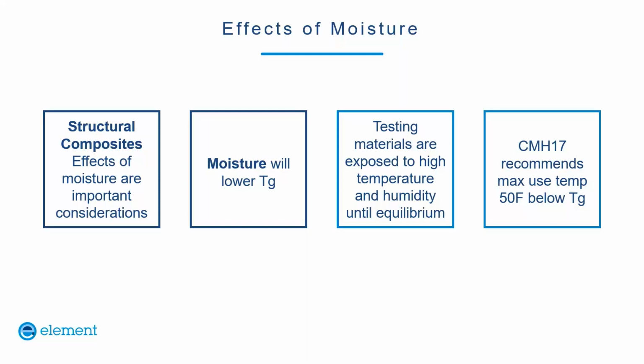And we can run DMA or other thermal analysis on wet specimens as well and determine the wet TG. Specific criteria for the weight gain are given in ASTM D 5229. CMH 17, the Composite Materials Handbook, provides guidance for FAA certification, and it's generally a base reference material. It recommends the maximum use temperature be 50 degrees below the wet TG.